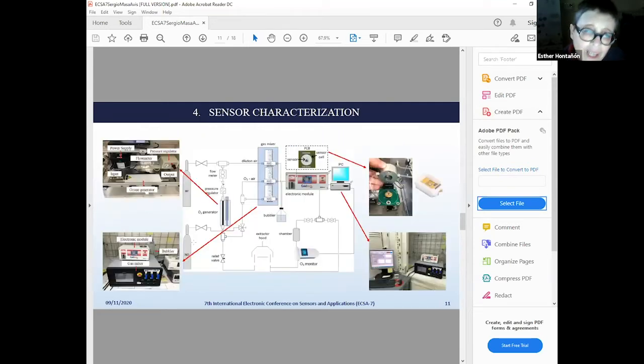Just the layout of the facility we use to perform the gas measurements, which is a standard one. We use gas mixtures of known composition. For nitrogen dioxide and carbon monoxide, one can use gas cylinders of calibrated mixtures. In the case of ozone, because it's quite unstable, it cannot be stored, so you have to produce it in situ, and we use a commercial ozone generator. The gas coming from the ozone generator or from the cylinders is mixed in a gas mixing unit with the clean air coming also from a cylinder, and then one can adjust the desired concentration of the target gas in the mixture. Also, the gas can eventually be passed through a bubbler in order to adjust the humidity of the gas. And the system is fully automated and is controlled from a program based on the LabVIEW software.